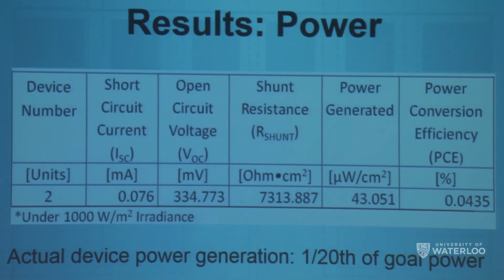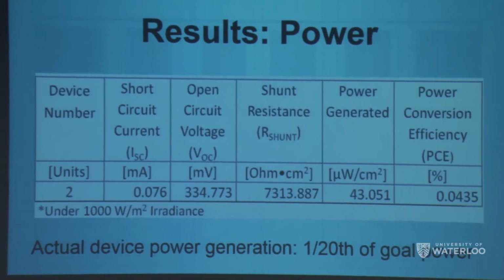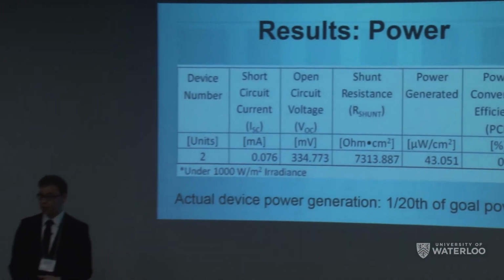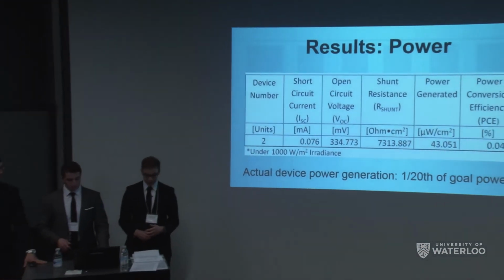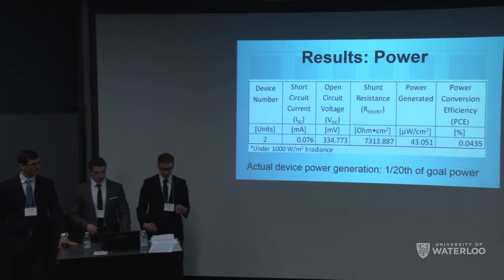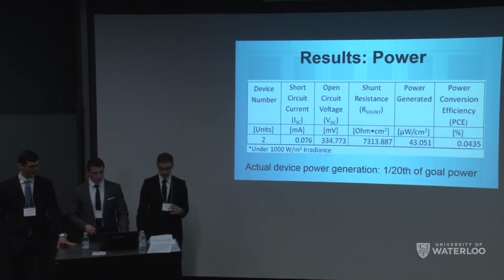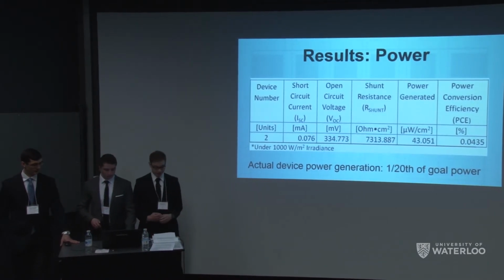Future work would involve optimizing the process parameters, such as the active layer thickness, the annealing method, and the ratio of donor to acceptor molecules, and we believe that this would improve the electrical properties by creating long-range order in the device in the active layer and reducing the electron-hole recombination.